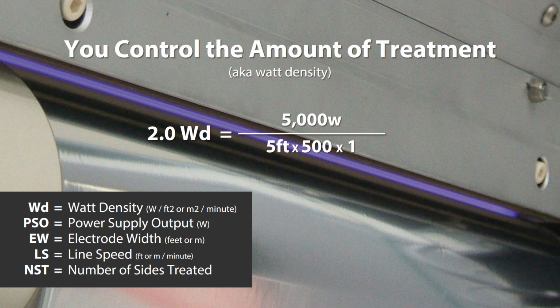Again, general point, but if you're running pre-treated film and you're just bump treating this material prior to silicone coating, as our example illustrates, likely somewhere in that 2 to 3 watt density will give you a great result. So if you can get yourself tuned into this sizing method, this measurement method, and you use this on a regular basis for your key products, and you tie it in with a peel adhesion number, a dyne number, maybe a contact angle number, if you tie these data points together on one page, you end up with some very powerful data that can help you troubleshoot in the event you have a problem. Next slide.